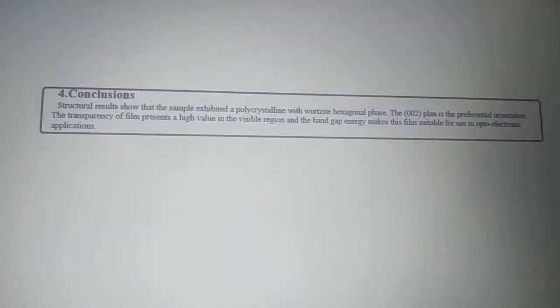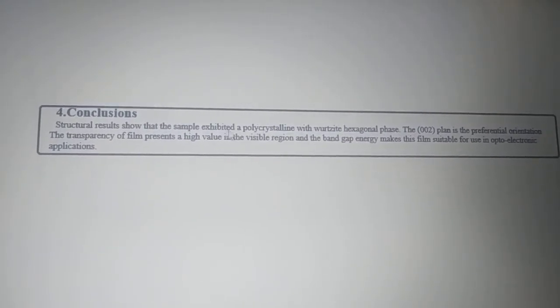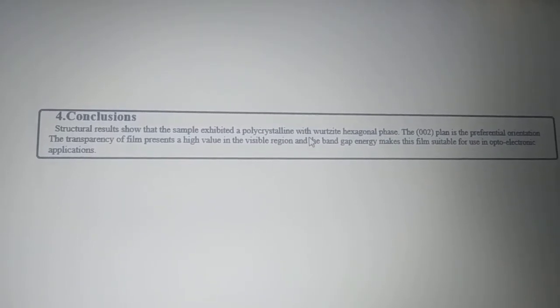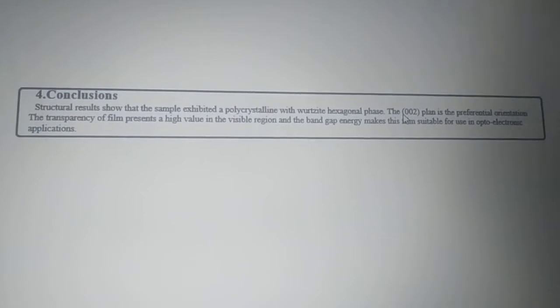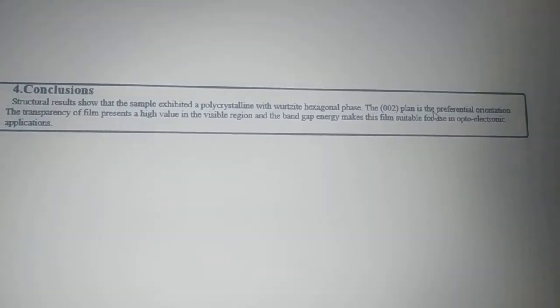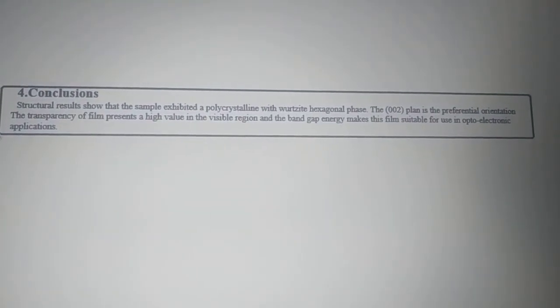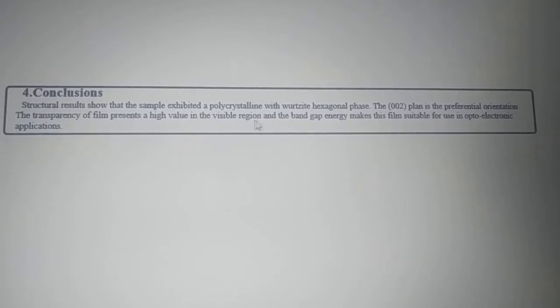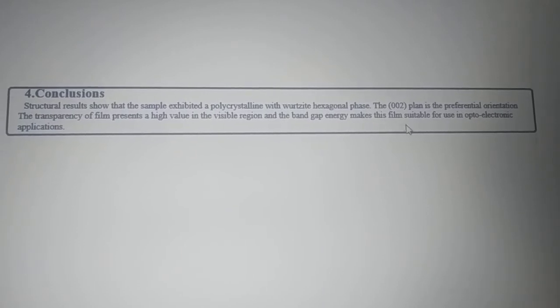Conclusion. Structural results show that the sample exhibited a polycrystalline with wurtzite hexagonal phase. The 002 plane is a preferential orientation. The transparency of films presents a high value in the visible region, and the band gap energy makes these films suitable to use in